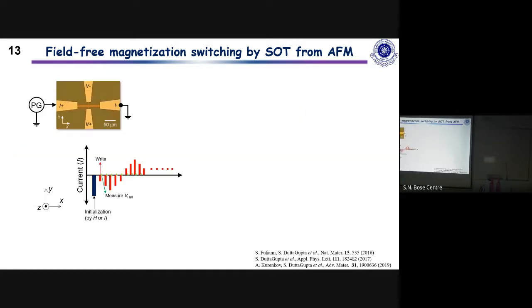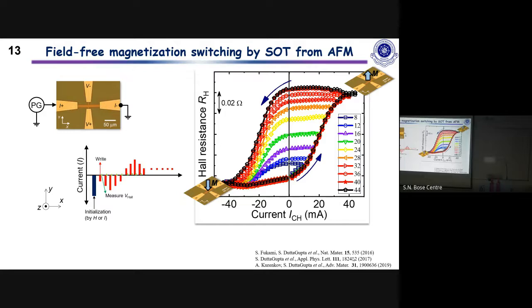So then what we did was we made the same type of devices, called Hall bar devices, and based on the experiments that we have, we don't need the magnetic field for the concept that we want to show. So we first initialized the magnetization of this area by applying an out-of-plane magnetic field or current, and then we just sweep the current along this direction. We don't apply any magnetic field for this experiment. And this is our experimental result. Starting from the down direction of magnetization, as we sweep the current, we see that the magnetization goes from down to up and then comes back.